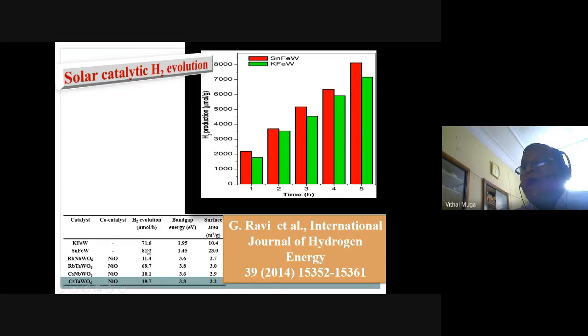And band gap energy. Now, I told you a few minutes back that SrTiO3 is a benchmark material for water splitting. About 200 micromoles per hour it gives, whereas our sample gives about 81, which is less than 50% of that. But you look at similar materials published elsewhere, they have used co-catalyst, and their hydrogen evolution is much less than our materials without co-catalyst. And this result we published in the International Journal of Hydrogen Energy, an Elsevier journal having an impact factor of about 5. About 5 is actually a very decent impact factor. And I am talking about the impact factor by Thomson Reuters, not a predatory impact factor.